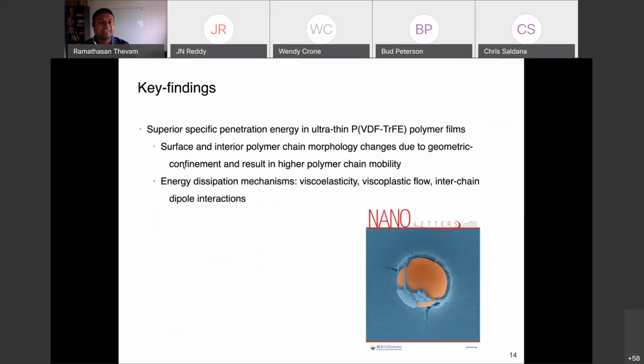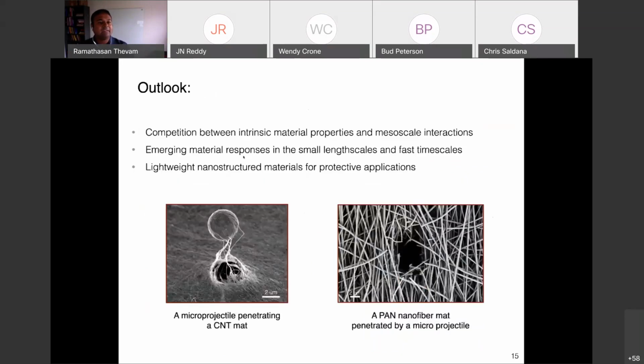So what you have seen is a very high specific penetration energy due to this polymer chain morphology change as well as the crystallinity change, and it engages a lot of viscoelastic and viscoplastic deformation as well as dipole interactions in the piezoelectric material. So with this understanding, we want to go and study more complex systems like these nanofiber mats, both in polymers as well as these carbon nanotube type of systems. And we want to study the competition between the intrinsic as well as the extrinsic mesoscale interaction effects in this material system. So this is an ongoing study.